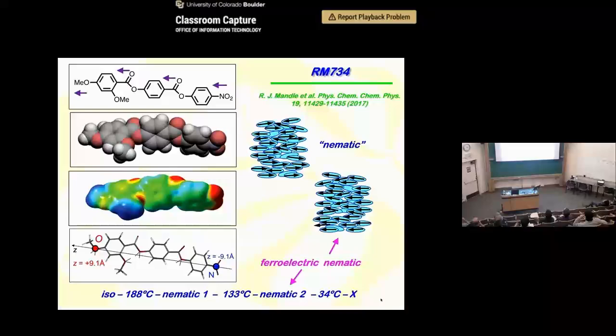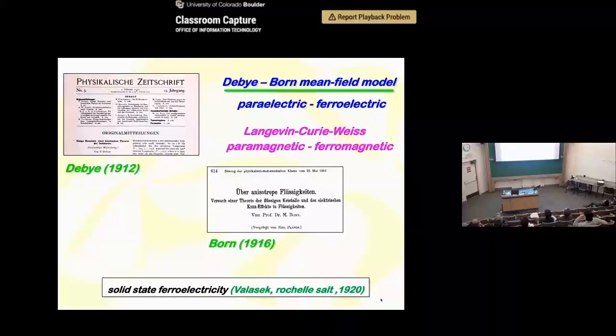Okay, so this transition has been in the liquid crystal literature for a long time, 120 years. So Peter Debye and Max Born in the 1910s wrote mean field models for that phase transition between the ordinary nematic and the ferroelectric nematic. They were trying to account for liquid crystal order in general. There was a small population of liquid crystal molecules at that time, and so the proposal was that you have liquid crystal ordering because of ferroelectricity.